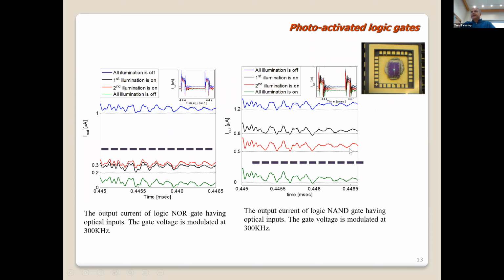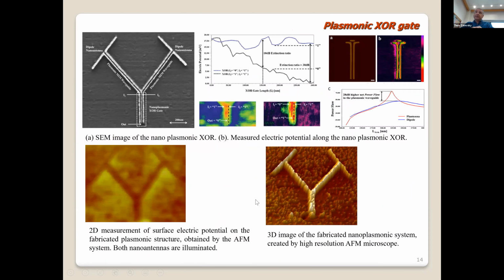Okay, and then by properly wiring this device, we also realize different logic gates like NOR gate and NAND gate, and here you can see the image of the fabricated chip and its operability as a logic gate. Another direction we investigated is plasmonic logic gates. We have developed special antennas that efficiently convert light into plasmons, and by properly connecting those antennas and generating special plasmonic waveguides, we could realize a plasmonic XOR gate. You can see here the measurement. After a propagation of approximately 150 nanometers, we have a modulation of the output with approximately 15 dB extinction ratio.